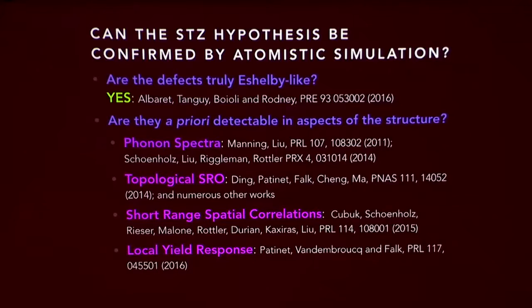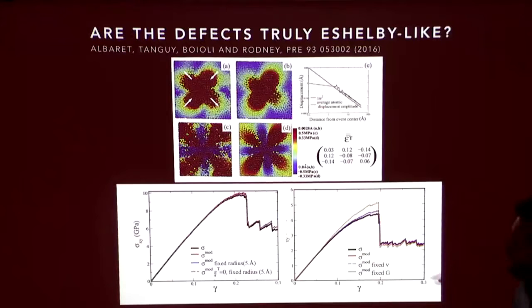Okay, yeah, so this is from that work, by amongst others, N. Tanguy and David Rodney and some collaborators. What they did was take a simulation of, in this case, a silicon glass, amorphous silicon, deform it in shear, and try to extract as they're deforming it. So this is still a posteriori—they're not going into the structure and looking for the defects from the beginning. They're shearing the system and looking for where deformations happen in the material.